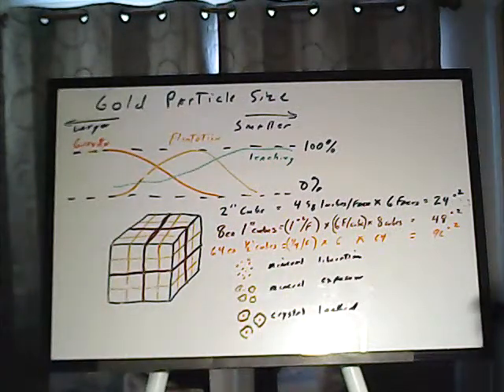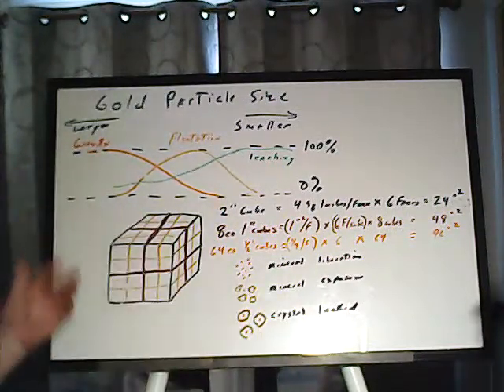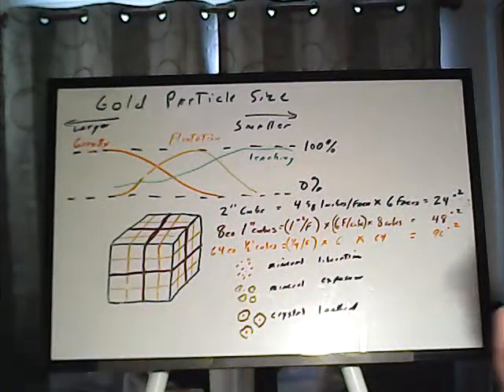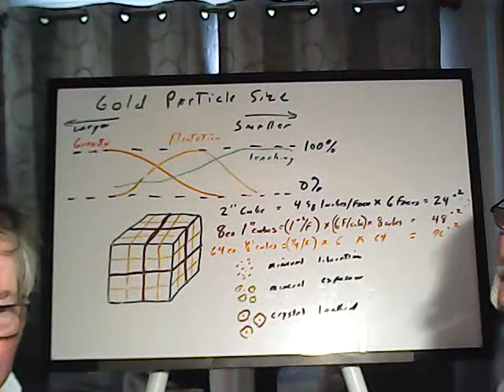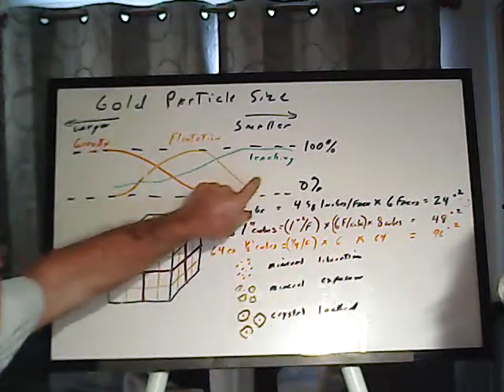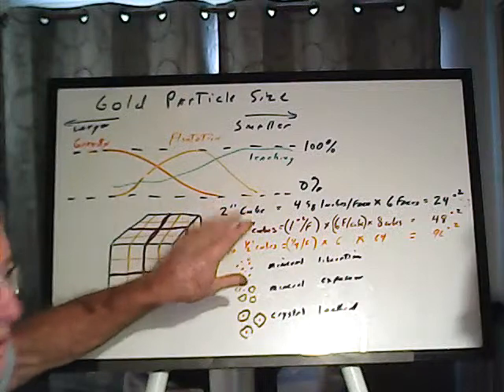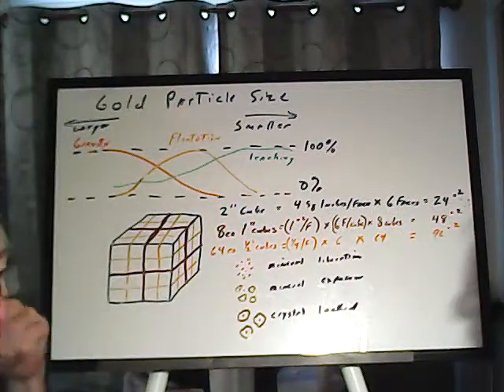Violent agitation helps because you're constantly scrubbing that off and grinding it up into smaller particles. And so that's why you would use leaching, because it works better on the fine gold that you can't get any other way.